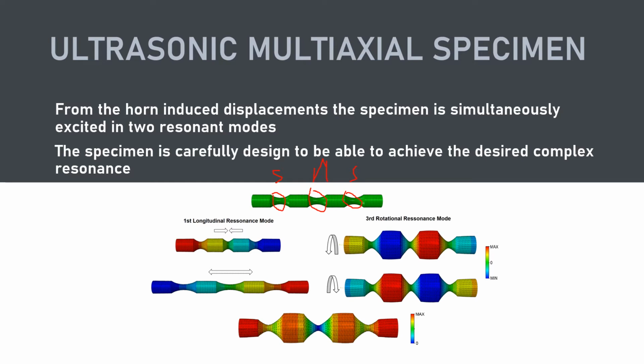Now the specimen having this geometry will have the first longitudinal mode for tension stresses. This is very similar to the tension compression ultrasonic specimen, and the third rotational mode where each cylindrical section will rotate in a different direction, thus inducing shear stress in all three throats, and the combination of these two modes create tension and torsion in the main throat.